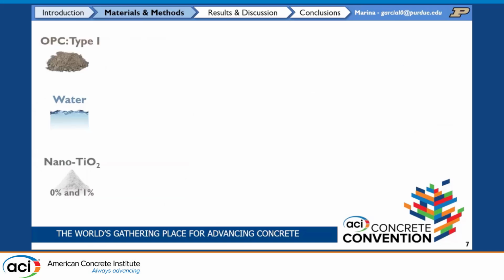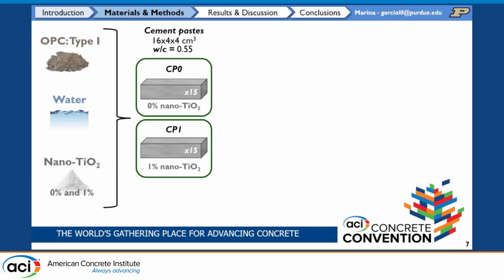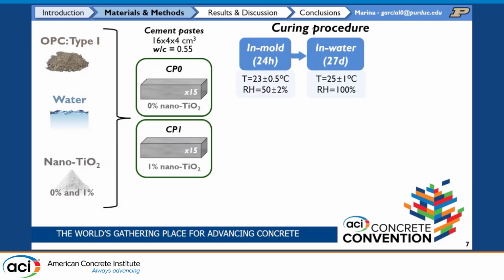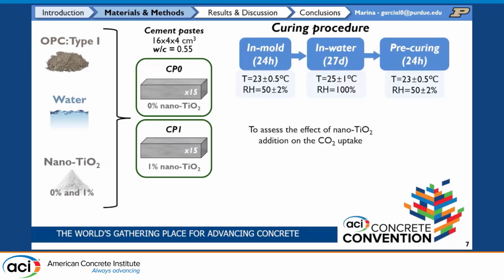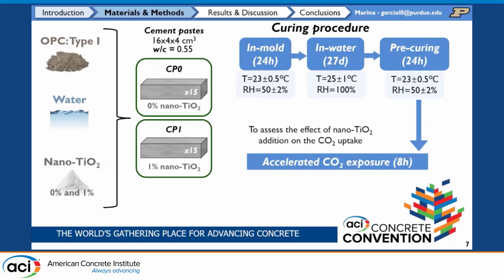So for the materials and methods, we used ordinary Portland cement, water, of course, because we're doing cement pastes, and titanium dioxide nanoparticles at 0%, so no nanoparticles, and 1%. We casted a total of 30 prisms, half of them with no titanium dioxide nanoparticles and half of them with those nanoparticles. As for the curing procedure, these samples stayed in the mold for 24 hours, then in water curing until the 28th day, and then we exposed them to a pre-curing treatment so that we could lower the internal moisture to prepare them for that CO2 exposure. To assess the effect of the titanium dioxide nanoparticles on this CO2 uptake rate, we exposed the samples after those 28 days and after that treatment to an accelerated CO2 exposure for 8 hours.